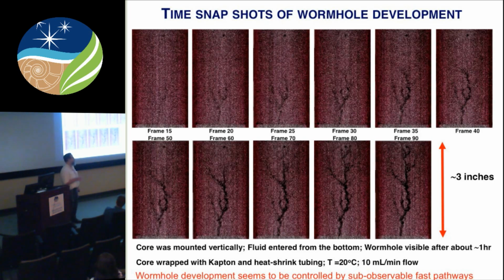And in wormhole formation, you've got a reaction that's happening quickly at rather fast flow rates. And what happens is you get a positive feedback loop, and the dissolution will essentially drill its way right through the rock. It happens because you get more flow where dissolution is already occurring. This has been modeled by lots of people, Tony Ladd, Carl Steefel, others have worked on this for a number of years. But in all of those cases, they've done that assuming this kind of homogeneous matrix. In fact, the original work that was done on this, where they did it experimentally, they did it in plaster, because it was the finest, most homogeneous material we could work on.